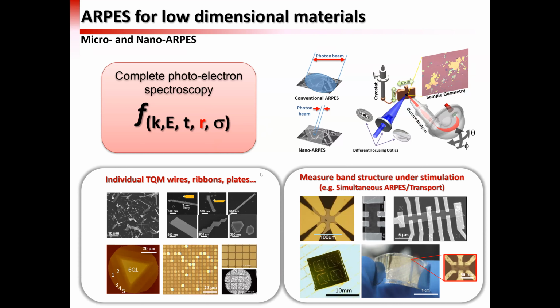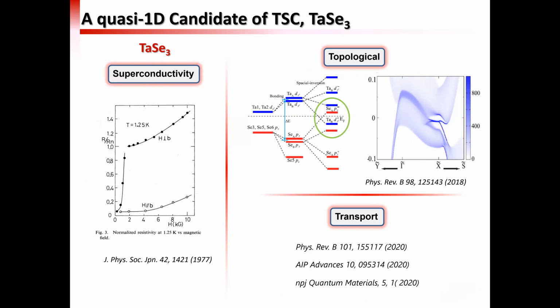But if we want to really study one single nanotube or a step edge, this could still be difficult, because even for the most advanced nano-ARPES facility, the beam spot is only a little bit more than 100 nanometers. Compared to the width of a nanoribbon or nanowire, that is still pretty big. So we still hope that we can get this quasi-one-dimensional material to crystallize into a 2D or 3D form, so that we can use micro or regular ARPES to study them. Basically, we want the nanostructures and 1D structures aligned in perfect order, so we can study them. The first example I want to share is tantalum triselenide.